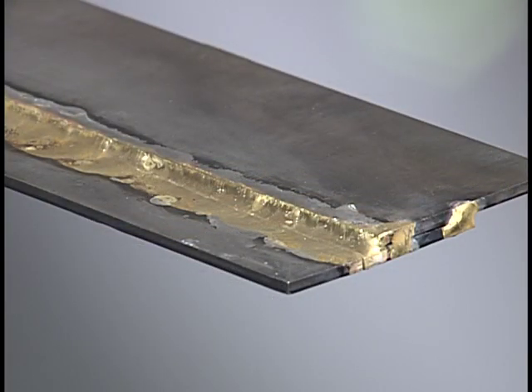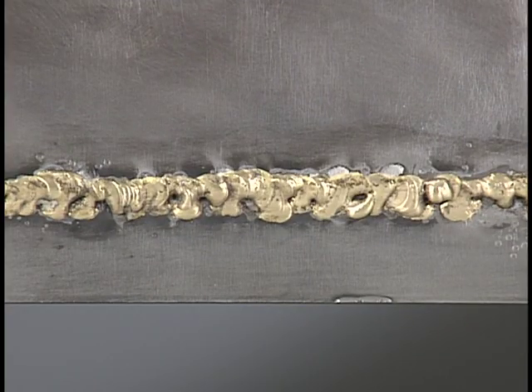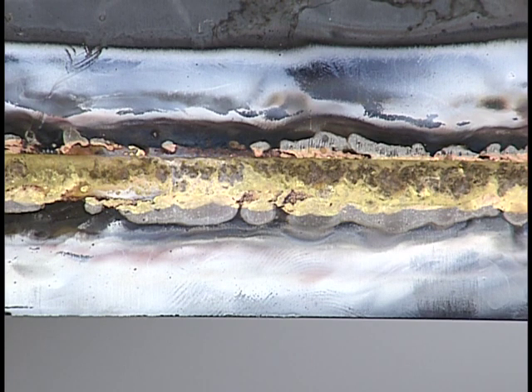If you add the filler metal onto the lower plate or direct too much heat there, the lower leg of the weld will be too long. Too fast a travel speed or not enough heat will produce a narrow, convex bead that does not bond with the workpiece at the edges of the bead. Too much heat will produce a rough, discolored weld. A white powder of oxidized zinc might be present, and the braze weld may be excessively concave on the face. Too much heat may also cause the braze weld to crack.